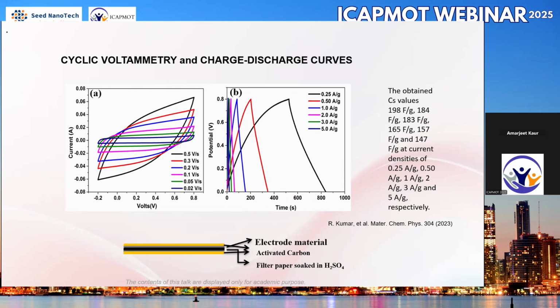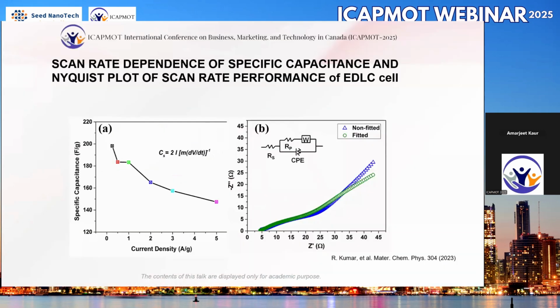This is the maximum capacitance value, Cs, we have obtained for the current density of 0.25 amperes per gram. If you look at the specific capacity versus current density, this almost remains constant for small current density values. So we try to develop a model for our device.